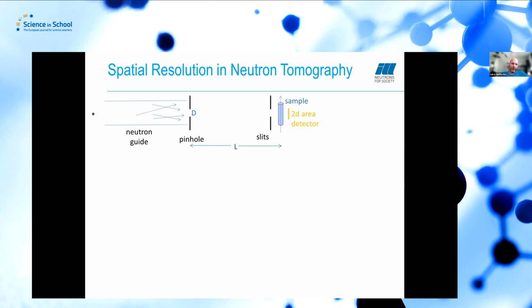Spatial resolution does not only depend on the detector system, but also on the collimation of the beam. So if you're looking at the neutron guide or at the cold source, they are very low brilliance sources. That means that the emitting source is quite large. The easiest way of dealing with that is to introduce a pinhole. So you have here a neutron guide getting the neutrons from the cold source to the imaging experiment. You create a total external reflection here in order to keep them in the guide, and then you have the diameter of the pinhole that defines the collimation ratio together with the distance where you put the sample in the end, the distance L here.